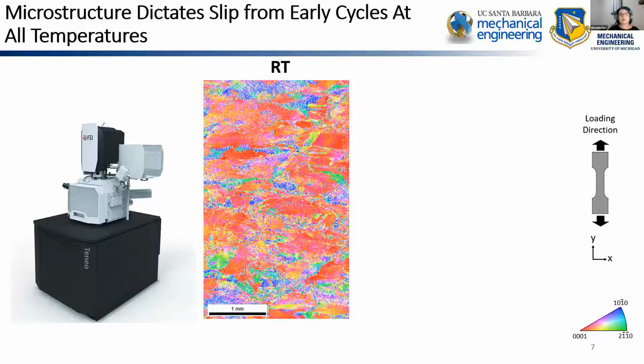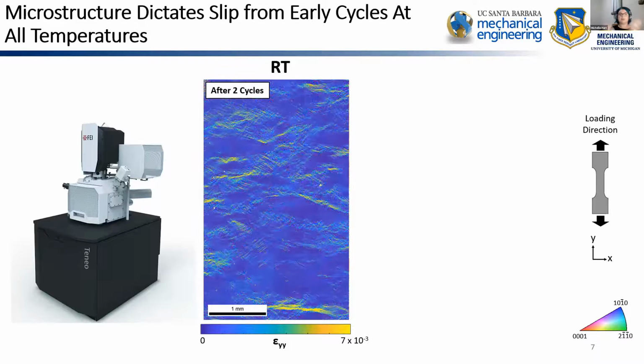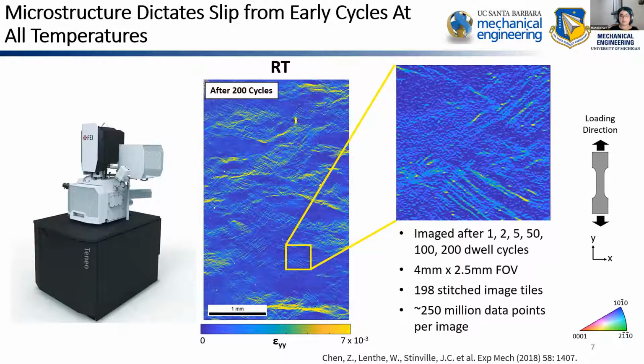So here is the orientation map collected via EBSD previous to starting the experiment. And then after two cycles, the sample was removed and I collected the digital image correlation over the entirety, and then placed it back in its loading condition, loaded some more, and then removed it again and looked after 200 cycles. Something that's important to note about these strain maps is that they're over that entire 4 by 2.5 millimeter gauge section, made up of about 200 individually stitched tiles, and there's about 250 million data points per one of these images, meaning that we have the resolution and the information that we need to look at these individual slip traces and investigate and identify them over the entirety of a very large, statistically significant microstructural area of the sample.